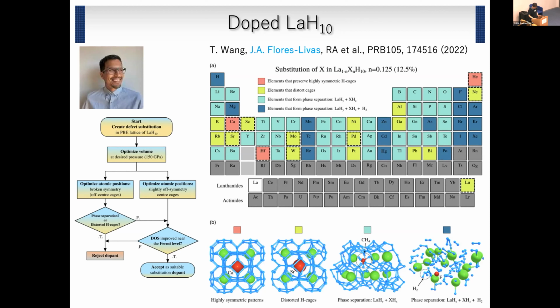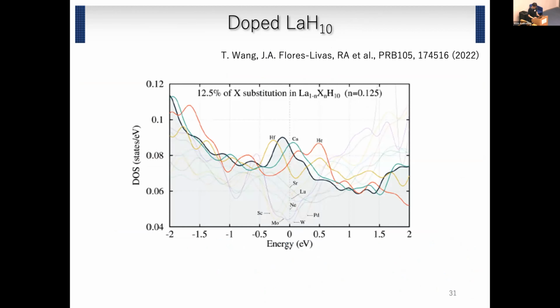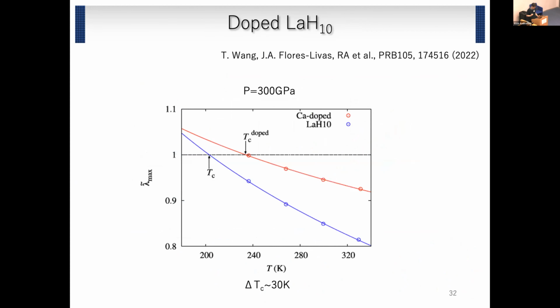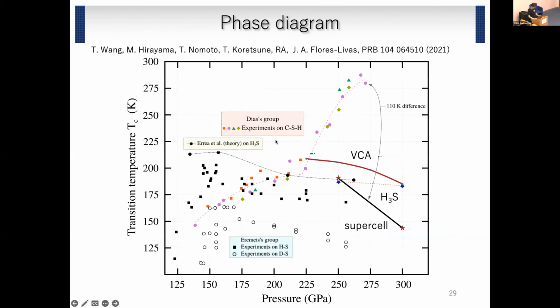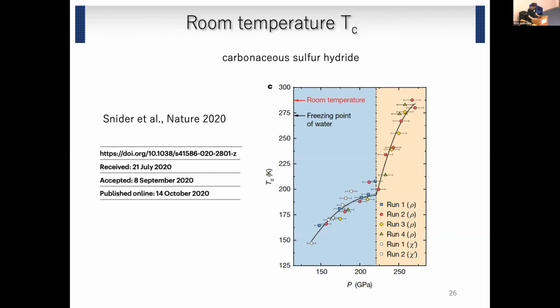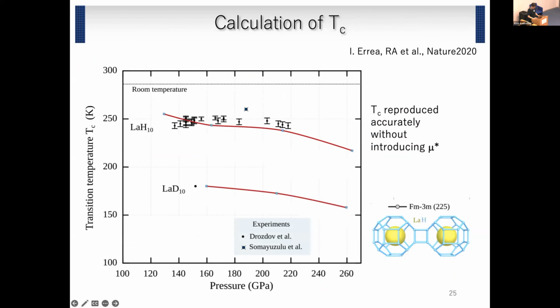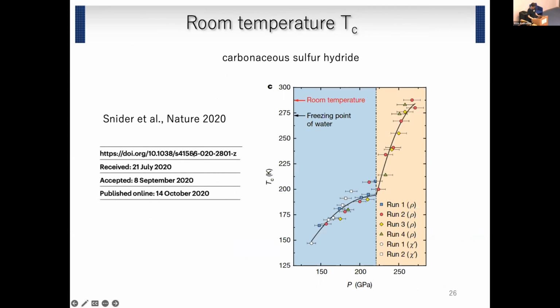And if we calculate the density of states, then, for example, in the case of calcium, the peak becomes close to the Fermi level. And if we calculate TC, then again we found an enhancement of TC of about 30 Kelvin. So this is a calculation at 300 gigapascal. But if we have an enhancement of TC also at about 150 gigapascal, then we can have room temperature superconductivity.